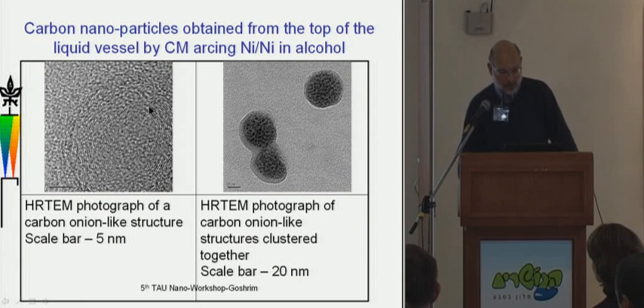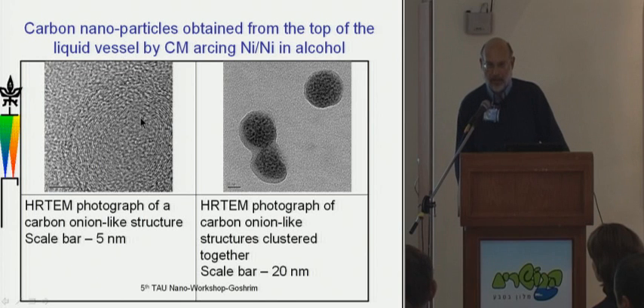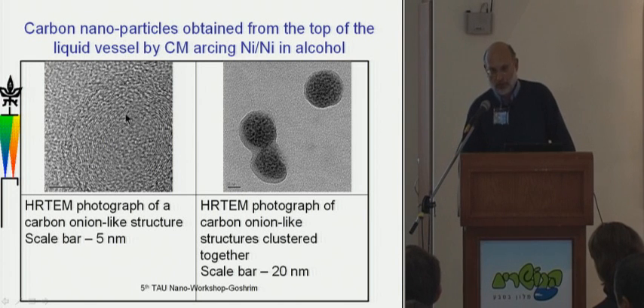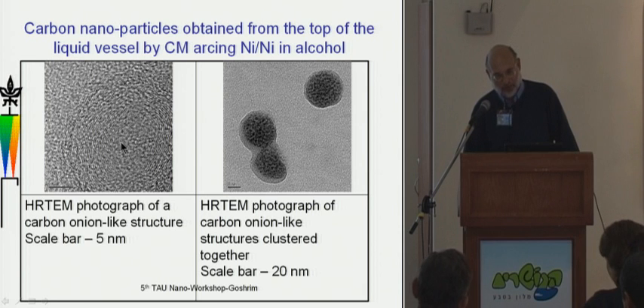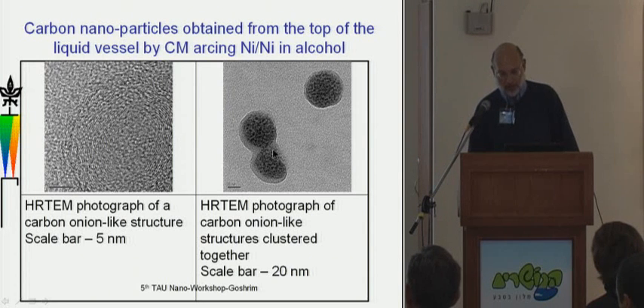If we do the discharge in alcohol, we can form what we call nano onions. I don't know how good this shows up. With a little bit of imagination, you can see these circles. This is sort of like a fullerene inside of a fullerene. Okay, think of a multi-wall carbon nanotube, but spherical. And that's what we have here. The scale bar here is about 5 nanometers. Sometimes these tend to cluster together in a liquid, and you get clusters of these things.